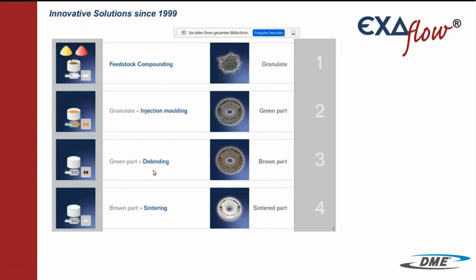It's a debinding oven, a debinding process. It's a chemical catalytic process. The granulate includes 80% metal powder and 20% binder. 10% is wax, and 10% they do not tell us what it is. But during the debinding process and the sintering process, it shrinks 22%.